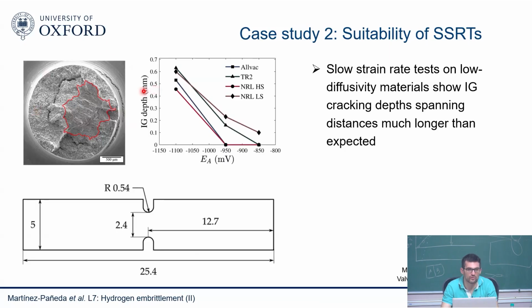So they look at the fracture surface and they see what areas have been embrittled. And eventually your crack is big enough that it will just grow unstable even through ductile processes and so on. But you do see an embrittlement region, and this is the area where you see intergranular cracking. And they can see that they get relatively large intergranular depths.